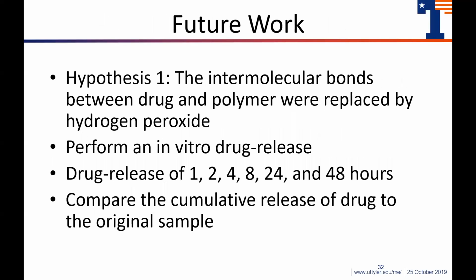So for our future work, we actually have two hypotheses that we're looking at. The first hypothesis is that the intermolecular bonds between the drug and the polymer are actually being replaced by the hydrogen peroxide. To determine if this is true, we'll be performing an in vitro drug release. This drug release will occur at 1, 2, 4, 8, 24, and 48 hours. And then we'll compare it to a cumulative release of the drug from just the original sample. Then we'll know if the drug release is faster. We'll know that the intermolecular bonds between the drug and the polymer are being replaced, and this release would be faster because the drug is now sort of free floating inside the polymer. And if it's the same or very similar, that will lead us more towards hypothesis 2.